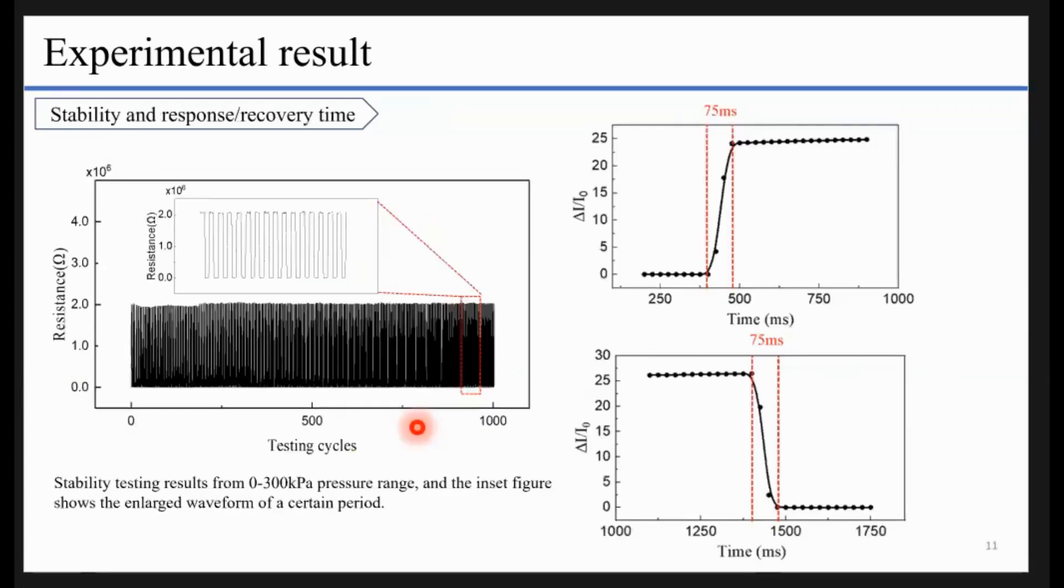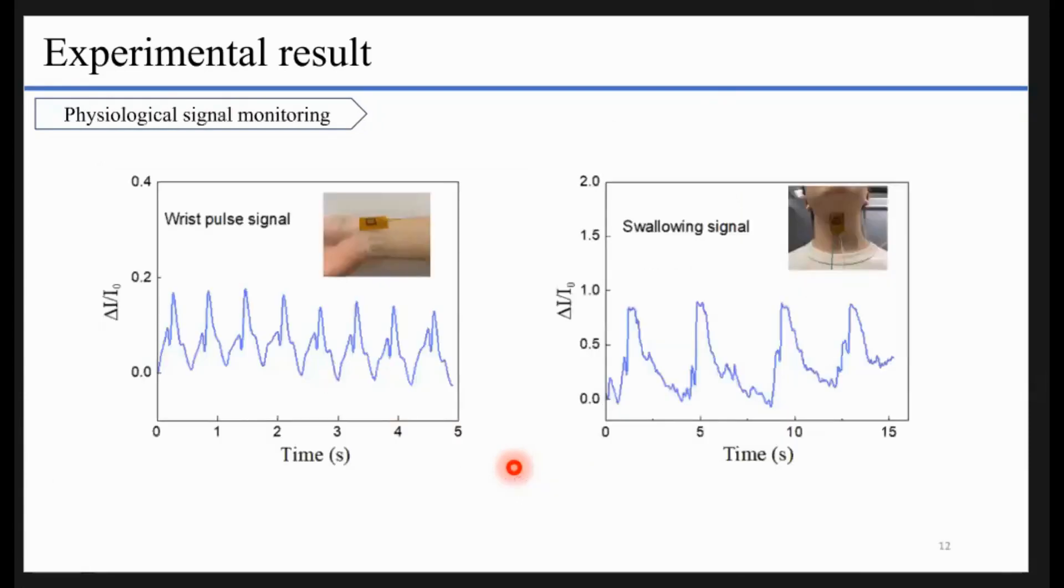Here is some stability test and response time test. We did a thousand times of repeated press. It shows good stability. The response time is very fast, around 75 milliseconds. We also attached them to the wrist to detect the pulse signal, and attached here to detect the swallowing signal. It shows good performance.